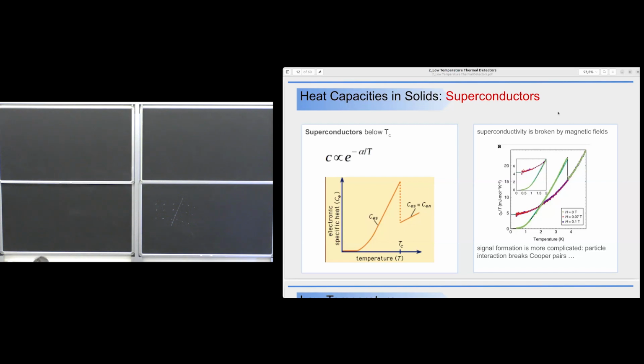Yeah, I mean, yes. I will go back later on this. I have two slides, so just wait for a while, and then if it is not clear, you can ask me again. So then we have superconductors. What happens in superconductors when there is the transition of your material to the superconducting state, you have this behavior, and then you have a temperature decrease that is exponential. So in principle, superconductors are good materials to be used as absorbers. However, the main point here is that it's not easy to check that you are quite below the critical temperature. Sometimes the transition requires a lot of time.